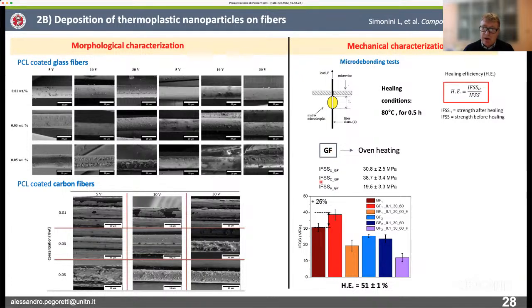Here you can see a summary of the result on glass fiber coated with nanoparticles of polycaprolactone. Positively, we observe an increase of the adhesion by the deposition of nanoparticles. And after basically the fibers matrix interface is damaged, we were able to reach a healing efficiency, which means how much of the initial adhesion we can restore, of about 50%. Okay, so basically half of the initial adhesion can be recovered by using these conditions.